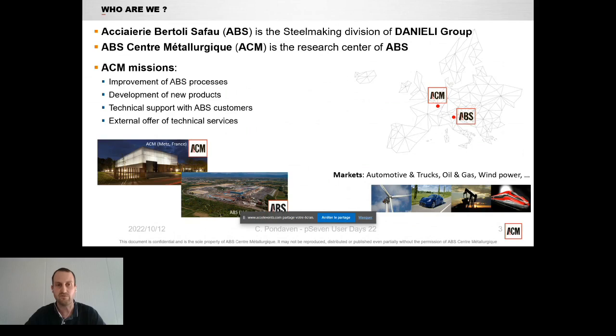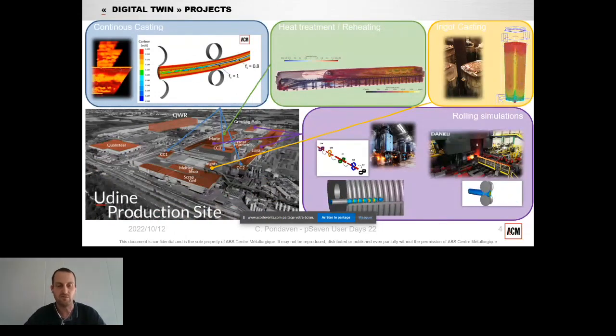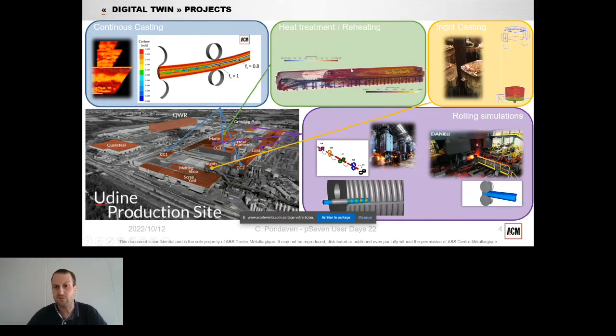So to improve ABS processes, we develop at ACM multiple simulation models of the processes of the Udine production site. For instance, we develop continuous casting simulation with the computation of the carbon segregation pattern after casting. We also perform CFD simulation of the reheating in walking beam furnace to improve their energy consumption. And we also perform rolling simulations, such as the simulation of grinding balls manufacture to avoid defects after the rolling and help to design the process to avoid also internal defects.